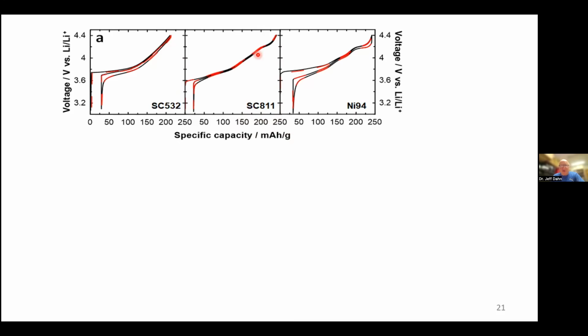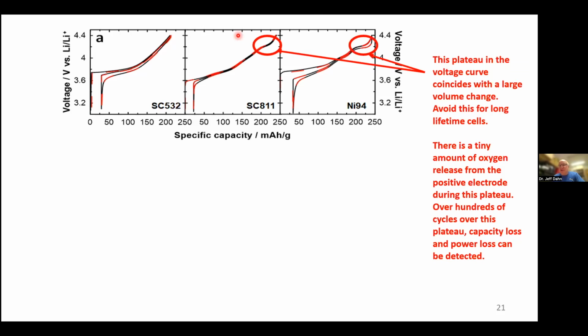Now, when you look at these curves, you'll notice there's one striking difference. These 811 and this nickel 94, they have this extra sort of plateau near the top of the charge, right? You can see it, and 532 does not. What's going on here? It turns out that the plateau in the voltage curve coincides with a large volume change in the positive electrode material. So this is a place where the positive electrode volume changes rapidly, and it's more likely to create microcracking if you go back and forth across this plateau. So you want to avoid this for long lifetime cells.